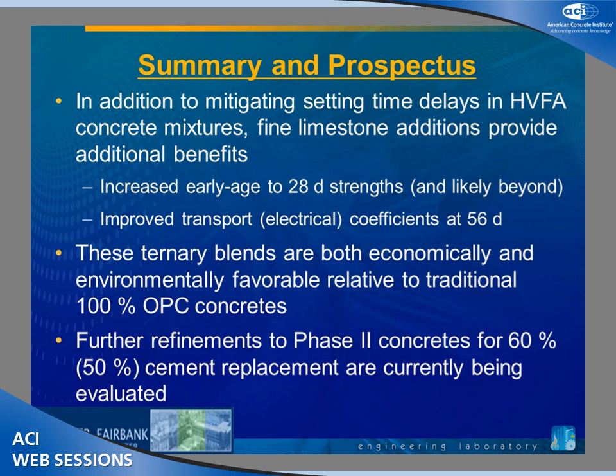And the other benefits that we're seeing, very good benefits in terms of increased early age all the way through 28-day strengths, likely beyond. We haven't measured those, but we anticipate that they will be higher. Improved transport coefficients at 56 days, and they are sustainable because they are both economically and environmentally favorable relative to 100% OPC concrete. So we're doing some more work with the Phase 2 concretes.